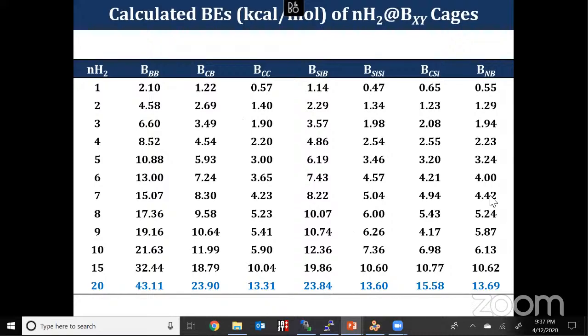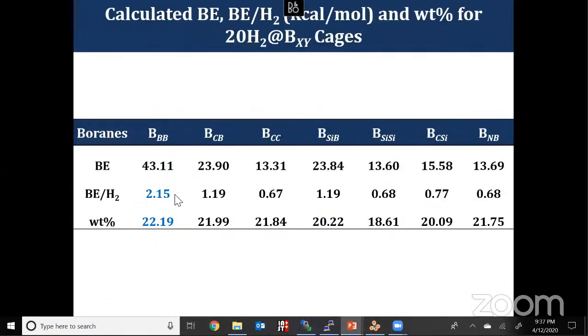So next, for the 20 hydrogen molecule adsorbed clusters, we calculated the binding energy per hydrogen molecule. Among all the clusters, the charged cluster has a higher binding energy per hydrogen molecule, but it's still less than the target value. The target value means the Department of Energy's.